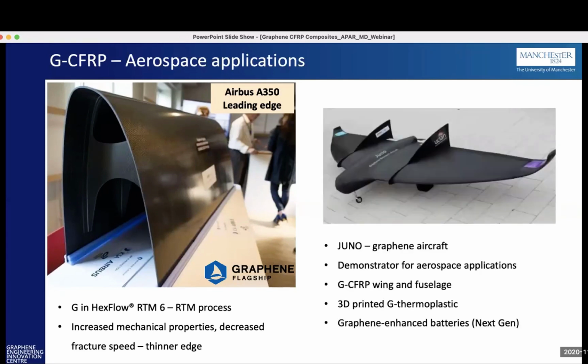So this is a UAV called Juno, which was developed by the University of Central Lancashire, along with Haydale and ourselves at Manchester University. As you can see from that, the prepreg is used in the fuselage and the wings as well. And also, if you look at the end of each of the wings, you'll see a blue sticker and a purple sticker, and those are actually 3D printed plastic parts, the winglets, which are then bonded onto the carbon fiber wings themselves.